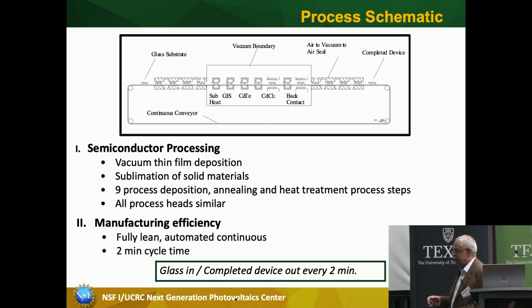And I'll show you later on. Arsenic does a slightly better job than copper, but copper, you can live with it. There are current production lines that run on copper, a slightly different form of copper than what we did, and you get one device every 2 minutes. So this fully lean automated manufacturing, this whole system as is, was commercialized, meaning that it was scaled to 2 feet by 4 feet, and it works in manufacturing in production.